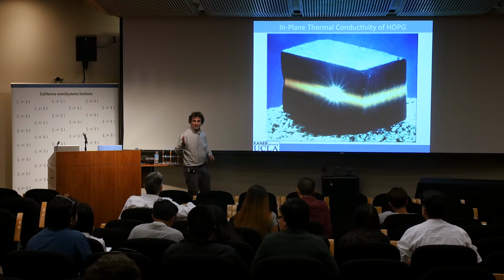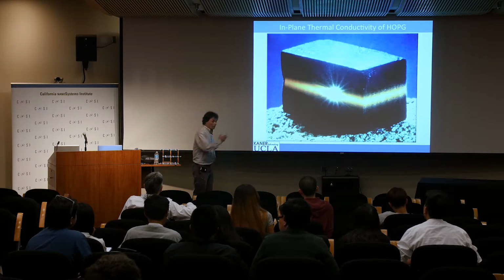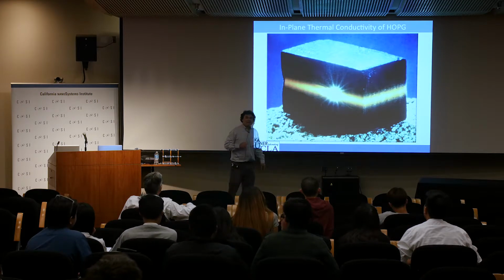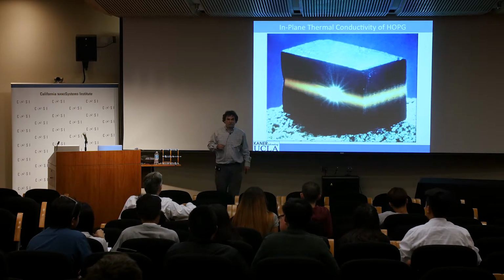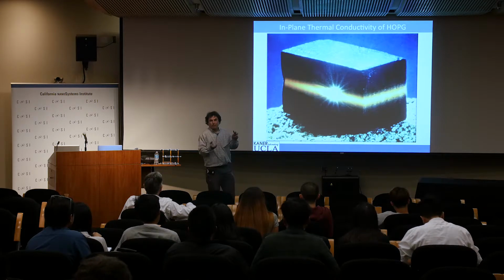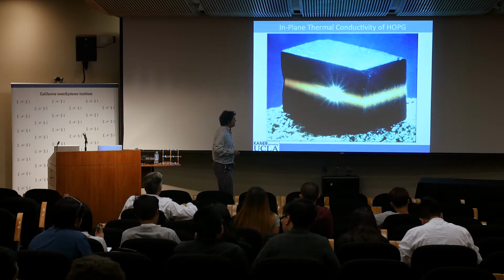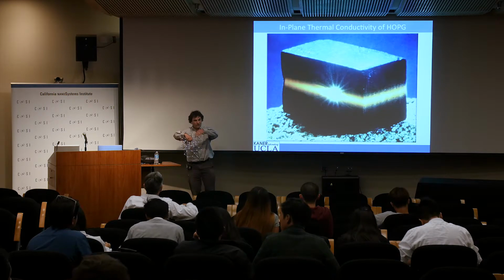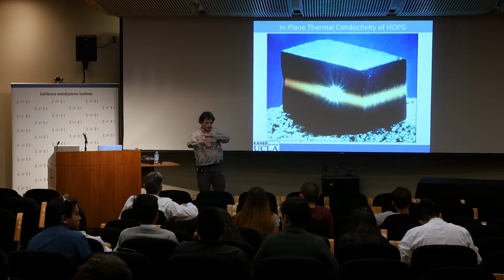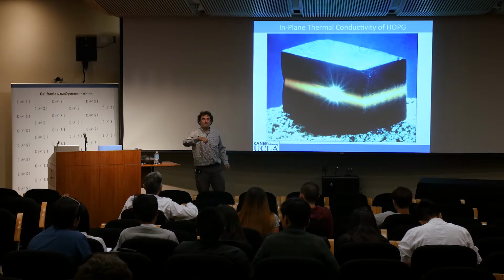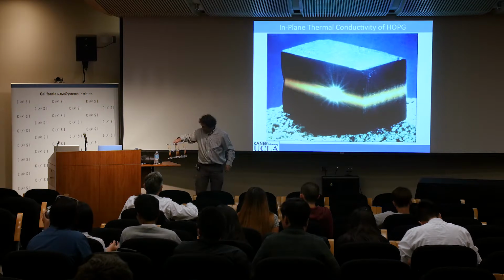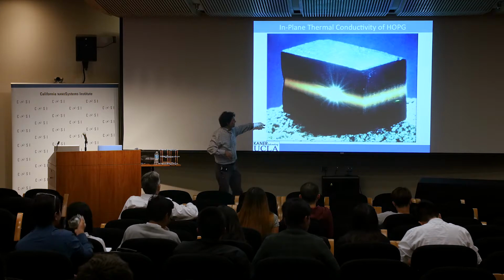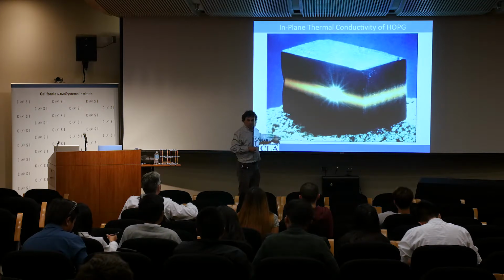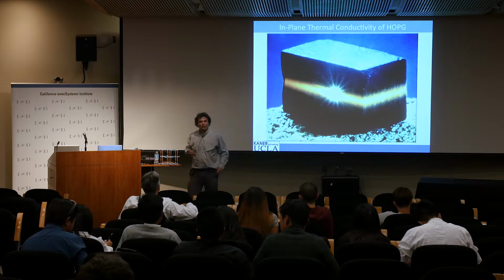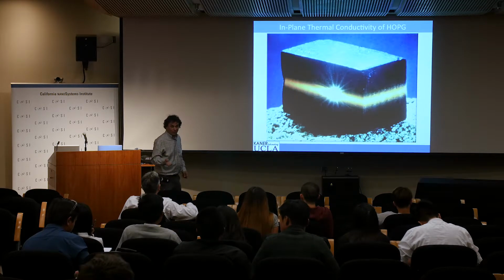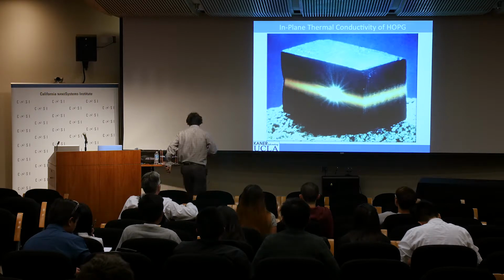And a normal material would heat up in 3 dimensions, but graphene, or graphite in this case, is not a normal material. So the heat follows 2 things. It follows what are called phonon modes, which are just chemical bonds, the bond stretches. And those all, of course, lie in this direction. These are not bonds, they're just van der Waals interactions. So heat goes this way, and it also follows conduction electrons, which are also in that direction. So you notice the laser hits here. If you touch over here, you burn yourself. If you touch the top, it's cold. And this is the only picture I've ever seen of a molecular property, or a nano property, if you will, in real space.